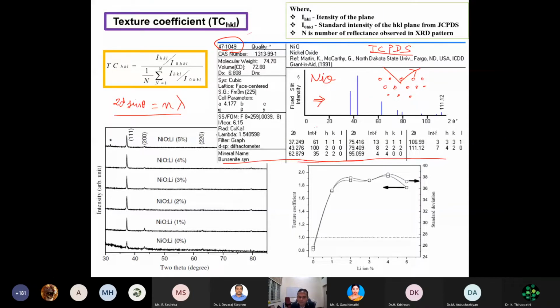Now here, for this polycrystalline material, you see that some of the peaks are there. The blue color lines are the diffraction maxima, and all others are minima. So this is the line position and intensity which I am supposed to compare with my film. If I make a thin film, not necessarily the same diffraction lines seen in the diffraction pattern of the powder material will match. This is very, very important. That is what is called textured growth. To calculate textured growth, we use a formula called the texture coefficient formula, which involves the intensity from the standard pattern and from our film.